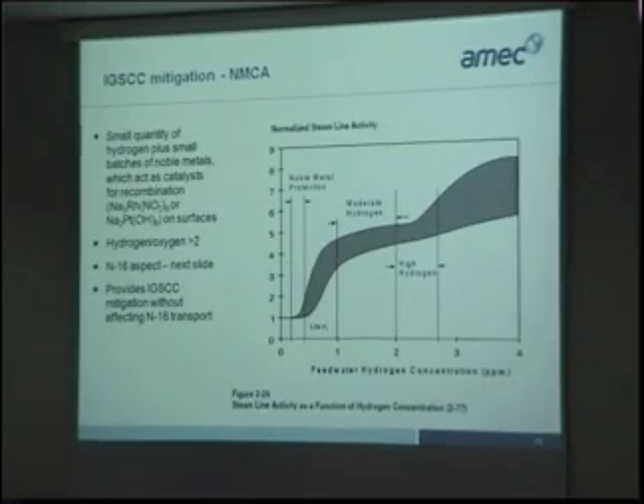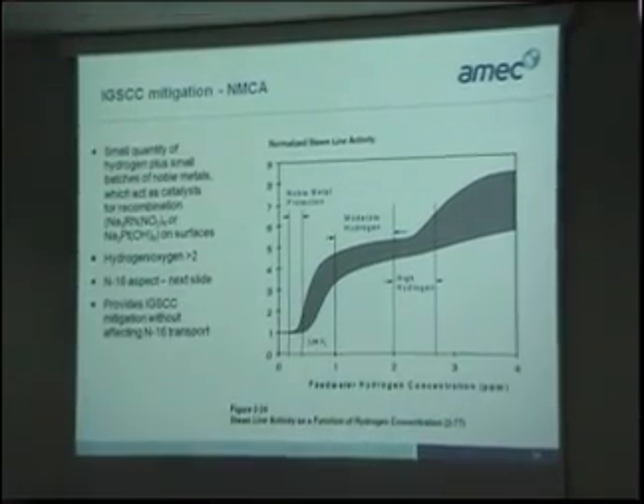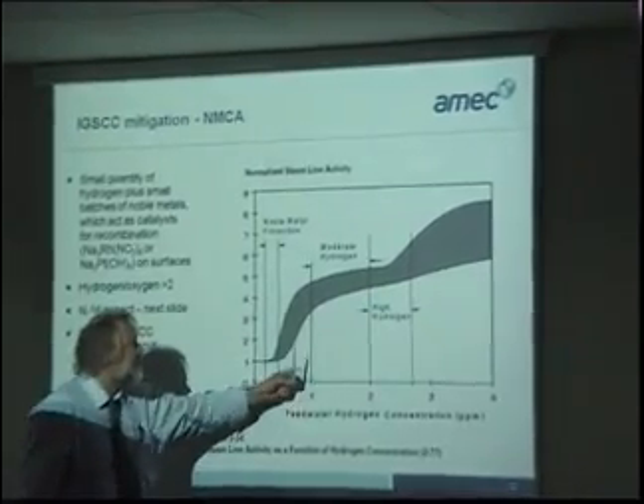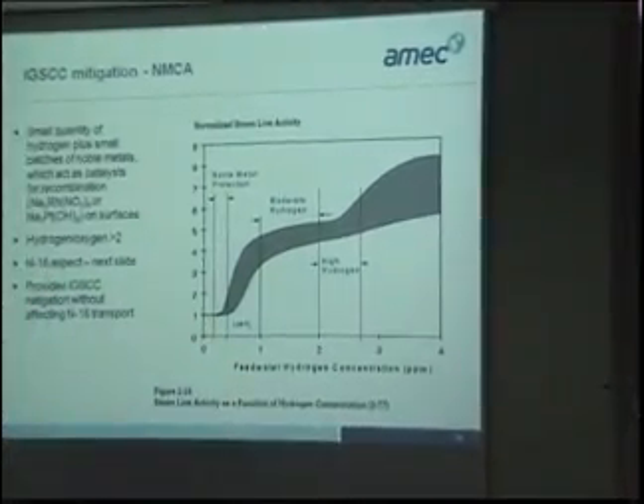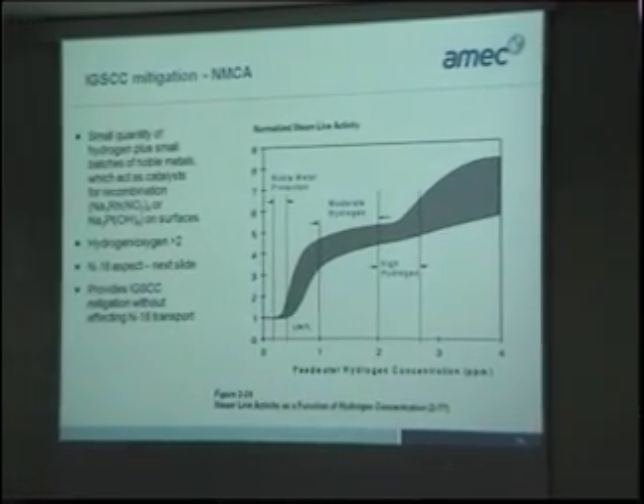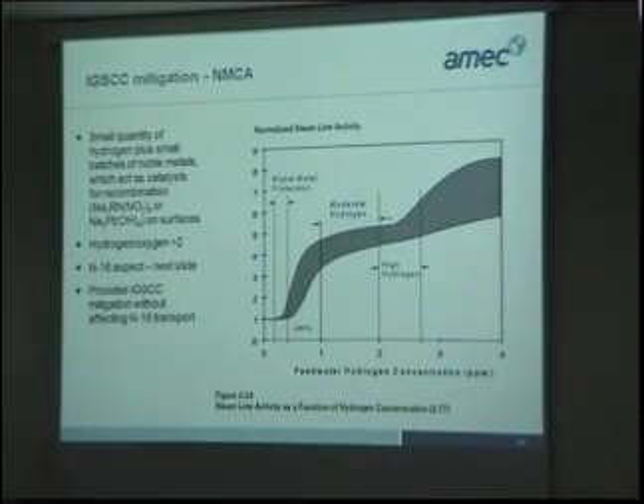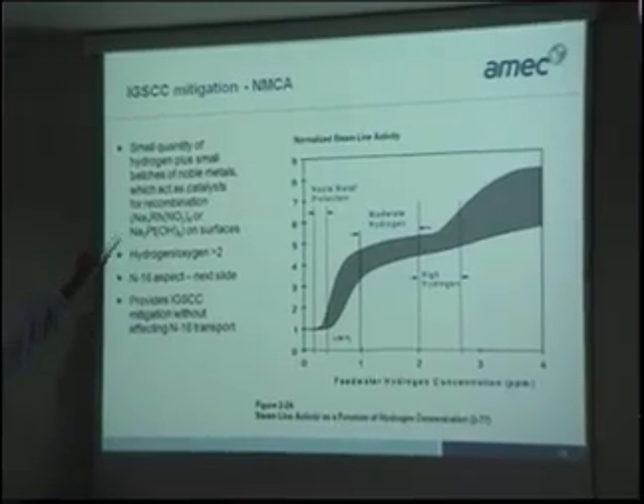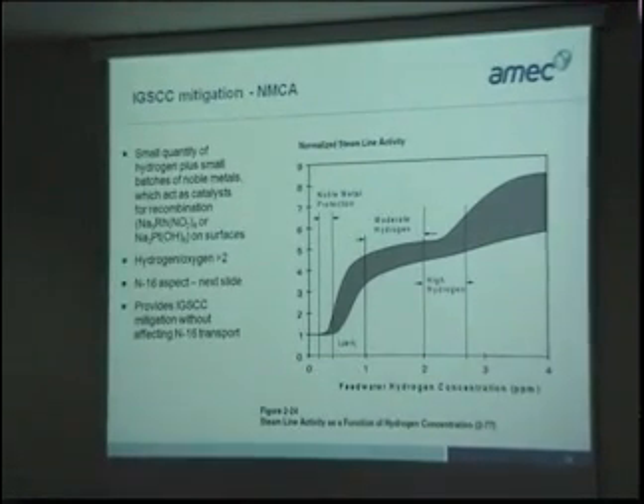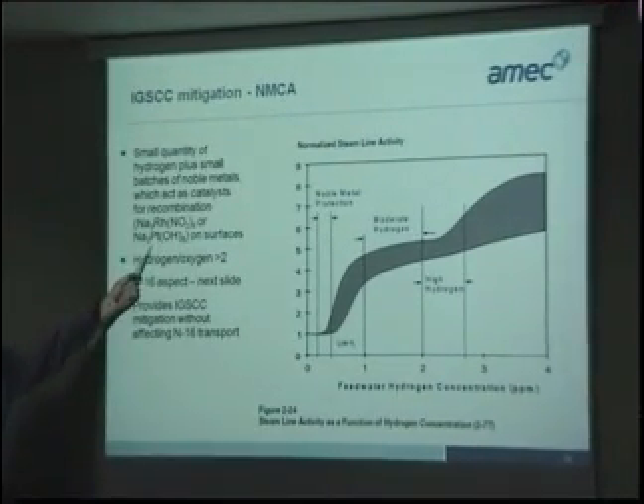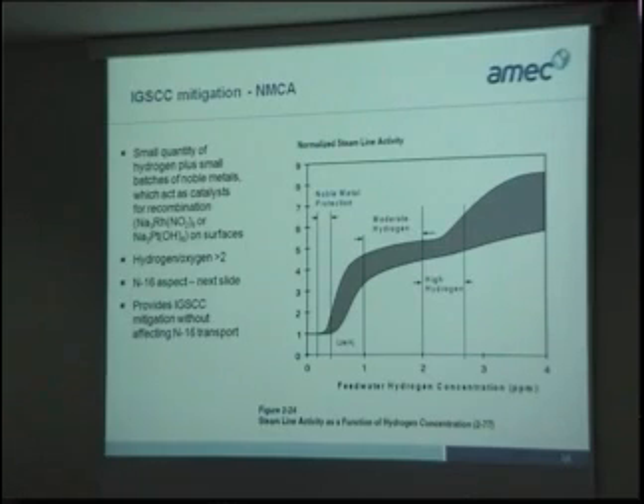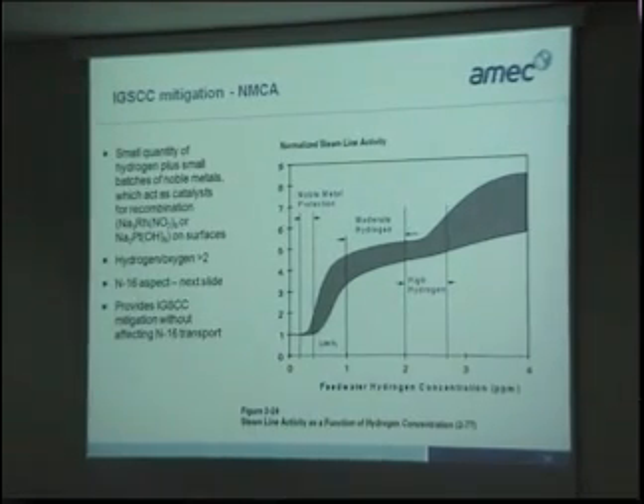And here we see the effect of noble metal protection. We did this with the high hydrogen, moderate, and low hydrogen, noble metal protection. It's usually this sodium rhodium nitrite complex or a platinum hydroxy complex that's added on the surfaces. At the moment it's done as a batch process, but there's a move towards continuous addition now of noble metals.